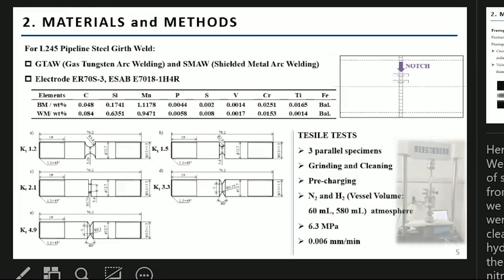Here is how we conducted the study. We designed specimens with a range of stress concentration factors from 1.2 to 4.9. For each condition we tested three parallel specimens. They were carefully prepared by grinding, cleaning, and pre-charging with hydrogen. The tensile test was then performed at 6.3 megapascal in both nitrogen as a reference and a hydrogen environment of 60 milliliter and 580 milliliter. The experimental result in a nitrogen environment is not sensitive to the volume of the environment chamber, so we conducted the experiment in a 60 milliliter chamber.